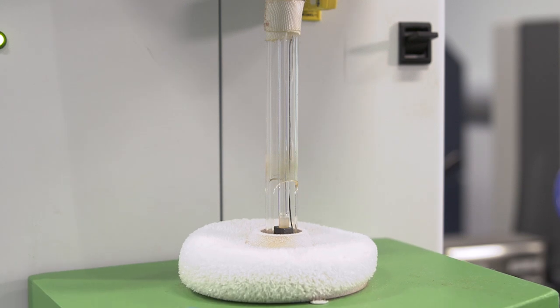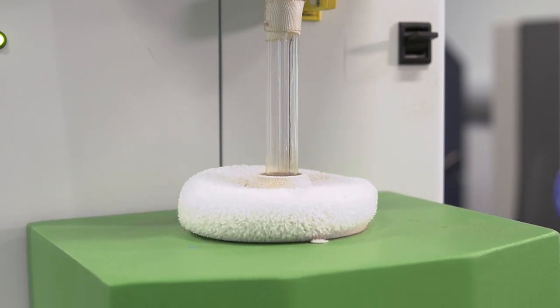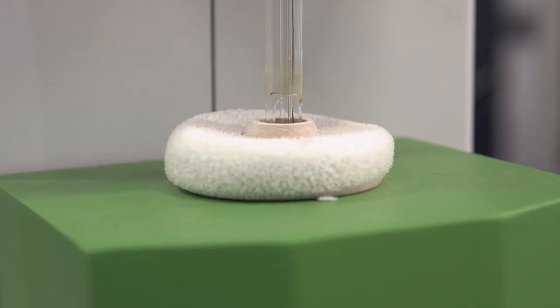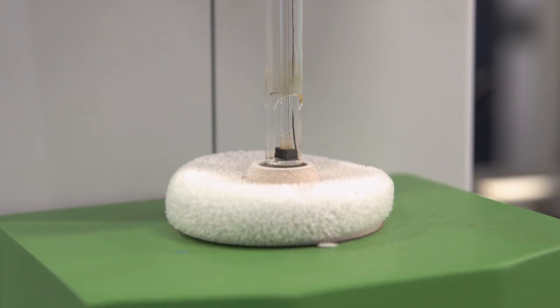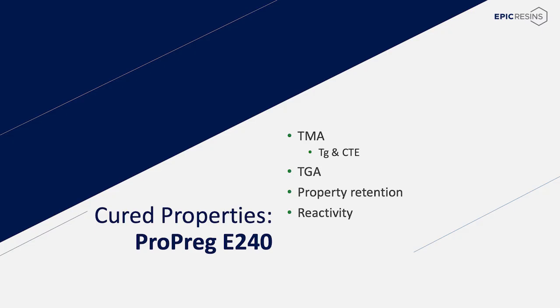The thermal-mechanical analysis, or TMA, measures dimensional changes in a material when ramped through a temperature range. In measuring thermoset epoxy polymers, the TMA measures the glass transition temperature, or TG, and the coefficient of thermal expansion, or CTE, of the cured polymer. The TG is the temperature when a material changes from a rigid glass-type material to a soft pliable material. The CTE is the rate of expansion over a temperature range.